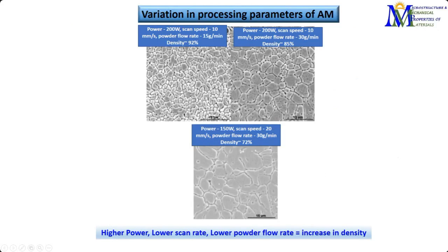So you see here, we are using the same power. These two microstructures, at the top, use the same power of 200 watts and the same scan speed of 10 millimeters per second, but there is a difference in the powder flow rate. The flow rate is higher, double in this case, and we end up having a coarser microstructure.